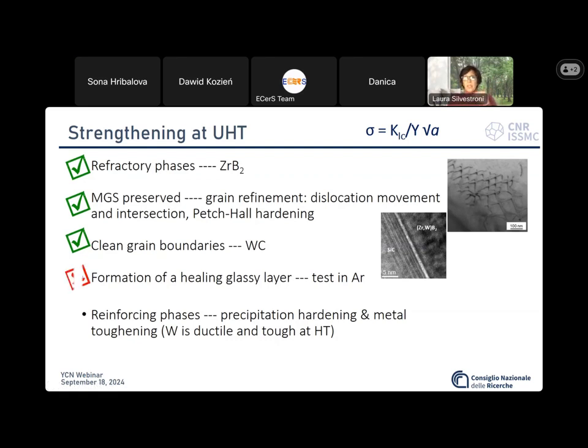Then we considered another hypothesis related to the formation of a healing outermost glassy layer at high temperature. But actually the tests were done in argon, and so no glass was formed. So this factor was discarded. Then we had a hierarchical microstructure with nano-sized tungsten particles acting as reinforcing phase. And this tungsten was ductile at the testing temperature and locally toughened the material.